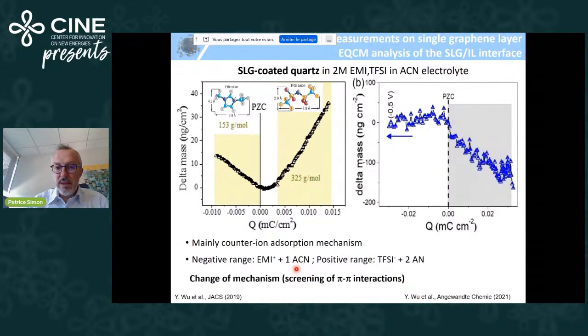And here, what you see is that if you remember what I presented before in neat EMI TFSI, it was a completely different behavior, with a weight loss for positive polarization and no weight change during negative polarization. And we simply changed the screening, we changed the pi-pi interactions, because in neat EMI TFSI the strong interactions between EMI and graphene come mainly from pi-pi interactions between the EMI plus and the sp2 carbon, but also alkyl chain interactions.